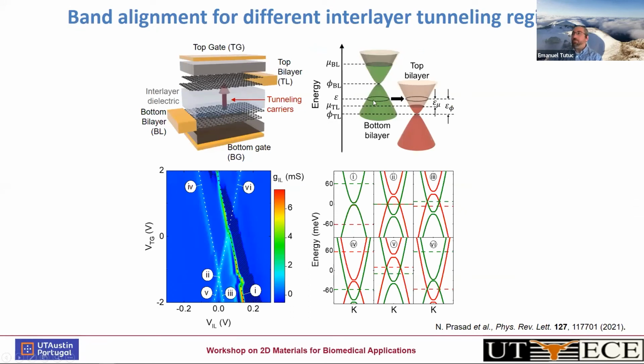And again, the physics of this tunneling can be explained by examining the band alignment of the two layers as a function of gate bias on one hand, top gate bias, bottom gate bias, or interlayer bias. The gates dope the different layers, and then an interlayer bias, a voltage difference between the top layer and the bottom layer, creates a Fermi level difference between the two layers. And this resonant tunneling, this very high conductance, occurs when the bands are aligned.